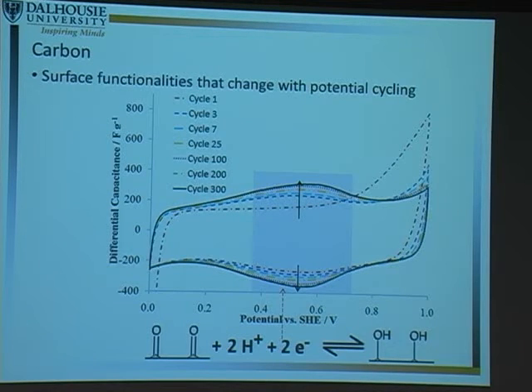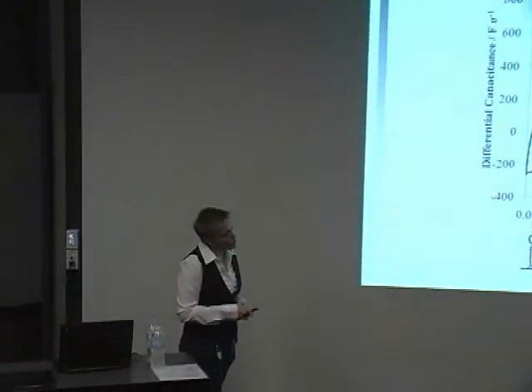And we know, of course, and I'm sure you've noticed, that as we do this CV, we have this very flat region, but we have a very large oxidation wave at these positive potentials, which disappears with cycling. And so one of the questions that we asked ourselves is, is this oxidation wave here related to those quinone peaks? Do we have a reaction on the surface? Are we taking the carbon itself and doing some sort of oxidation which is forming these quinones, or do we have a surface functionality that's redox active, which we're then converting to quinone groups, or are these two completely separate?